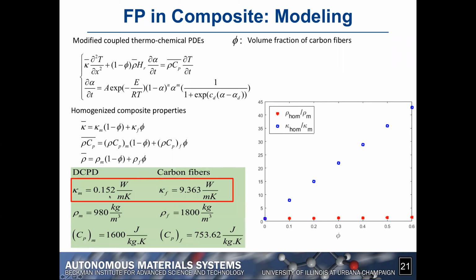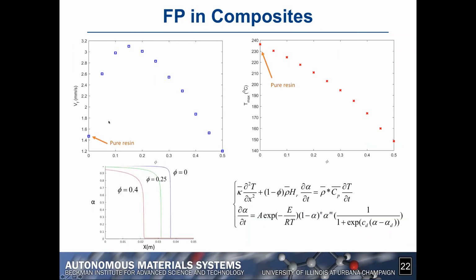And you can see here, it's almost 2 orders of magnitude difference. So as you increase the fiber volume fraction, the homogenized thermal conductivity of the composite increases quite drastically. There's also an increase in terms of the density, but that increase is not as high. So if we use this particular model and we actually solve these partial differential equations, we obtain these results. On the top left, you have the variation of the speed of the front as a function of the amount of fibers, so the fiber volume fraction phi.